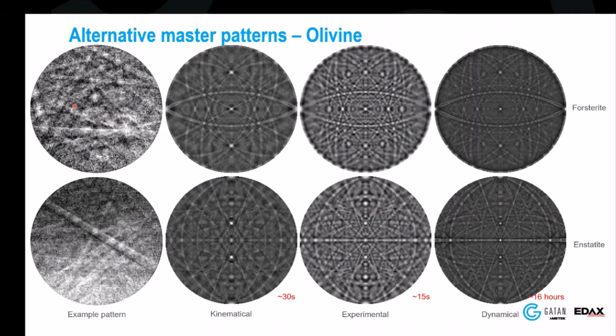And here you can see these patterns that we're using to build these off of. Over here, I have an olivine pattern, and of course, I have a whole data set with this that we turned into this master pattern. And here's the enstatite down here that we turned into this one over here. So instead of having to rebuild this dictionary or dynamical simulation every time, I can just use the experimental side and go from like 16 hours of reconstruction to less than a minute.